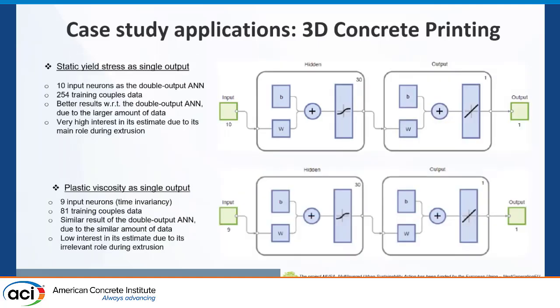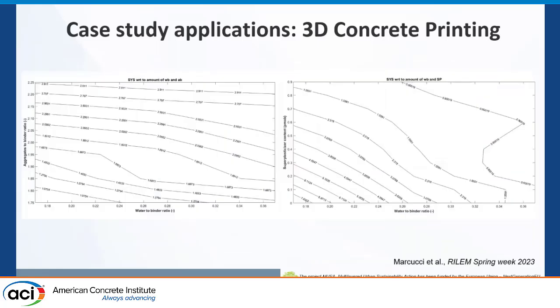So then we simply said, okay, let's try to split the neural network in 2, having 2 separate networks with the same input but working on each different output. So one on yield stress and the other one on the plastic viscosity. And it worked well, and what we ended up with was what an engineer wants, a design card, because in the end, he has to say, okay, I have a mix. I want to see whether it's printable, and if it's not printable, I want to have some tools which guide me to adjust the composition in order to achieve my requirements, to achieve the printability.